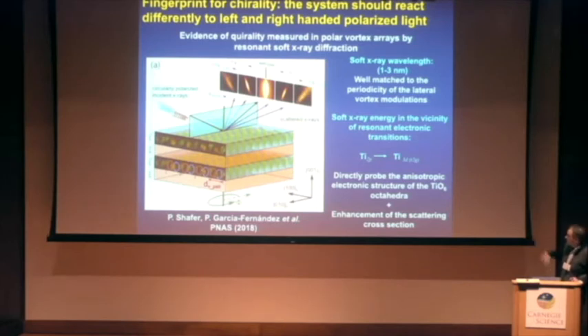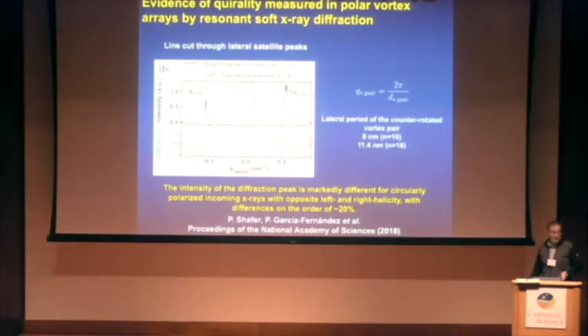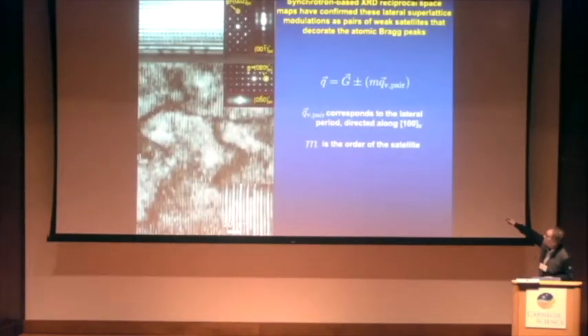So we can directly probe the anisotropic electronic structure of the titanium-O6 octahedra, and we enhance the scattering cross-section. So essentially here, those are the typical spots obtained from the XRD experiment. If we look at one of these spots in detail, we can detect the presence of satellites that are the signature of a superlattice, of a superstructure with the clockwise, counterclockwise vortices.